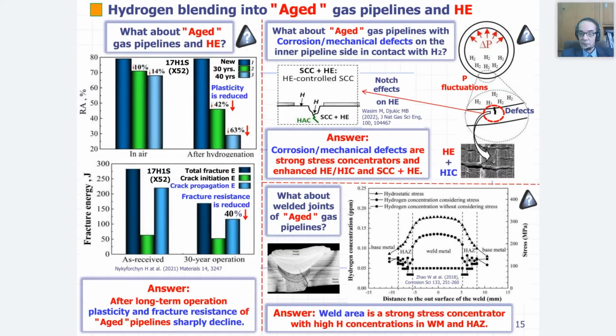Particularly important is the next question in the upper right part of the slide. What about the aged gas pipelines with corrosion and mechanical defects? As you can see, gas pipelines almost always have pre-existing defects on the inner side, corrosion defects in the form of gouges or some crack-like defects or mechanical defects, which have a substantial effect on hydrogen embrittlement.